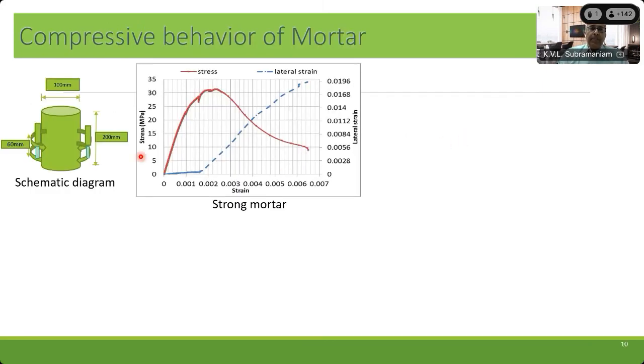Now, when we look at the compressive behavior of mortar, and you typically do a cylinder test or a cube test, this is what the compressive stress-strain response of the mortar would look like. What we did is we made two types of mortar, a weak mortar and a strong mortar. And I'll explain the reason why we tried two different forms of mortar. What's important to see here is the strong mortar, which is a little cement-rich mortar. And you see that the compressive stress-strain curve builds up to a peak and gives you a compressive strength of around 30 megapascal.